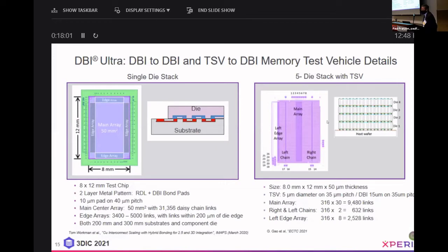With the die on the right, this is our stack structure. And in this case, most of our data is from 5 die stacks, although the structure could actually build as many layers as you wanted to theoretically. It has basically a bottom host wafer, and then TSV wafers, TSV die, which are 50 microns thick with 5 micron diameter TSVs. And those are stacked. On one side, they have DBI connected to the TSV, and on the other side, just the TSV, so that the first bond is DBI to DBI. The subsequent bonds are face to back, TSV to DBI, and then the last bond is TSV to DBI in what we call the cap wafer, which completes the daisy chain.